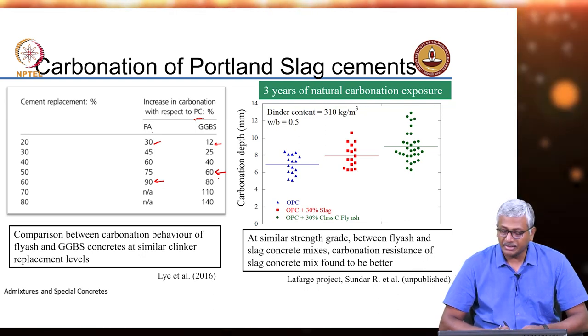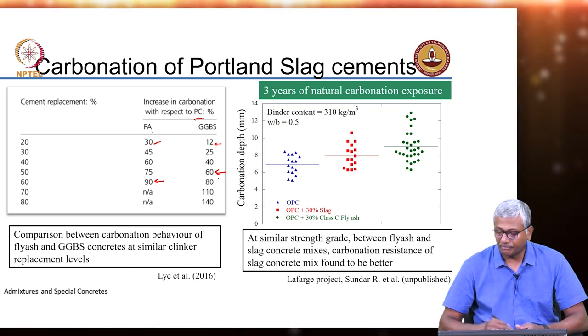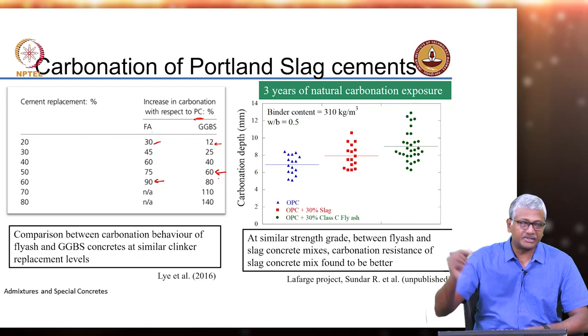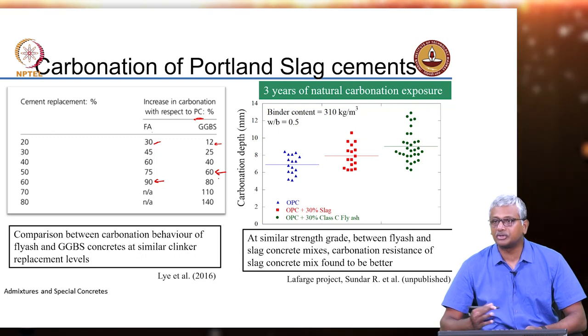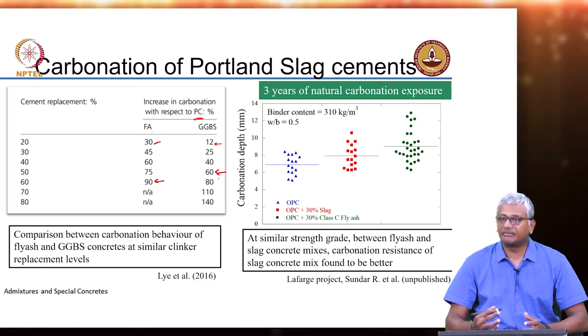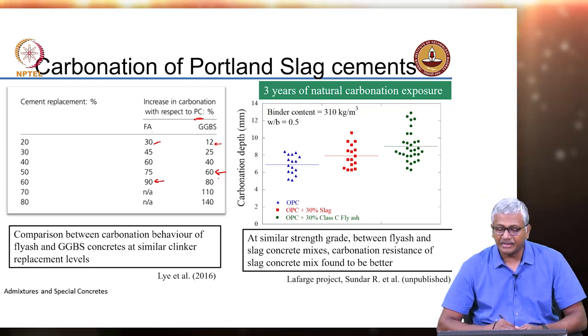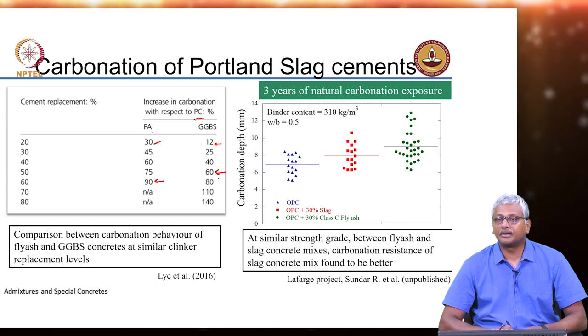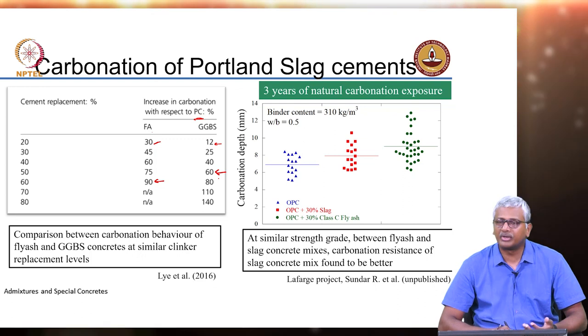At IIT, we had a long-term study done in conjunction with Lafarge Holcim. This study involved natural carbonation — our exposure site was essentially the terrace of BSB, where we kept specimens. After 1 year, 2 years, 3 years, 5 years and so on, we extracted specimens and checked the depth of carbonation. What you see here is, after 3 years of natural carbonation — what is the natural CO2 concentration? Approximately 0.04% or 400 parts per million. The CO2 concentration in an indoor environment is obviously more, depending on the number of people and air circulation.